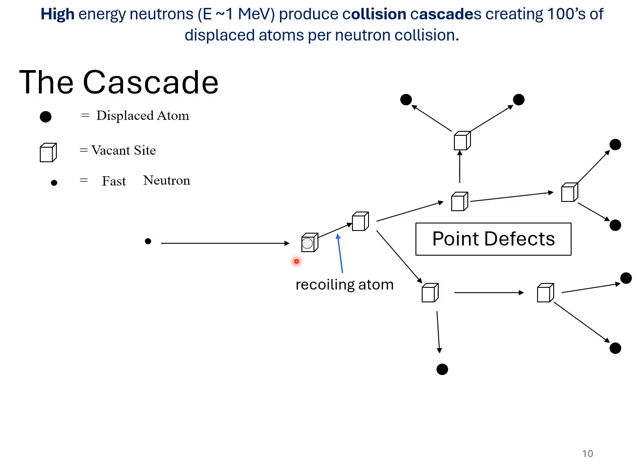There's a certain probability of that happening, of course, and it can impart some energy, to different degrees, because it may glance off or it may be a direct collision, just as you would have with a billiard ball table or a snooker table. Sorry, we are in North America right now, a pool table. So the energy needed to break bonds in atoms is around about 40 eV. So long as the incoming neutron can transfer more than 40 eV of energy to the atom, it will cause a displacement. But typically it produces many thousands of eV in the primary knock-on if it's a 1 MeV neutron, and then that goes on to create many displacements.